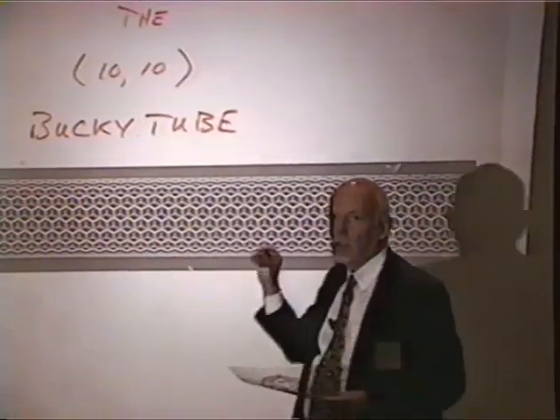One of the properties of these armchair tubes is that if you calculate the band structure of the tube, and I'll show you such a calculation in a minute, you find out that even though this is carbon, in the same structure that we're familiar with in graphite, unlike graphite, which is a single graphene sheet is a zero-gap semiconductor, and graphite itself is a semi-metal with a very slight overlap. This sucker is a metal.